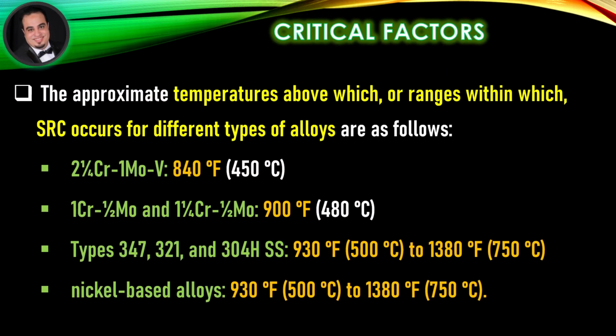The approximate temperatures above which, or ranges within which, stress relaxation cracking occurs for different types of alloys are as follows. 2¼ chromium 1 molybdenum vanadium, 840 degrees Fahrenheit. 1 chromium ½ molybdenum, and 1¼ chromium ½ molybdenum, 900 degrees Fahrenheit. Types 347, 321, and 304H stainless steel, 930 degrees Fahrenheit to 1380 degrees Fahrenheit. Nickel-based alloys, 930 degrees Fahrenheit to 1380 degrees Fahrenheit.